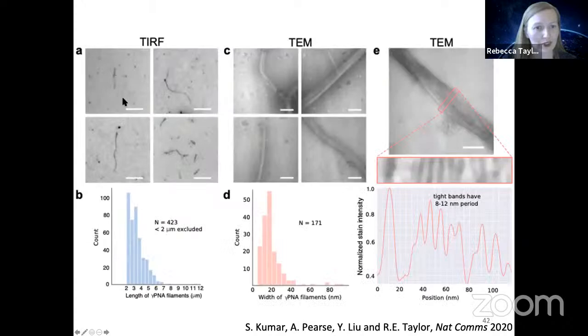And so sure enough, in fluorescence microscopy, we see these filaments, and I apologize for the lack of scale bars. These scale bars are 5 microns. So this filament is longer than like, you know, on the like 9 to 10 microns. And these are some of the longest we saw. Typically we'll see many in the range of a few microns, right? And then when we did TEM to sort of zoom in, we saw something surprising, right?